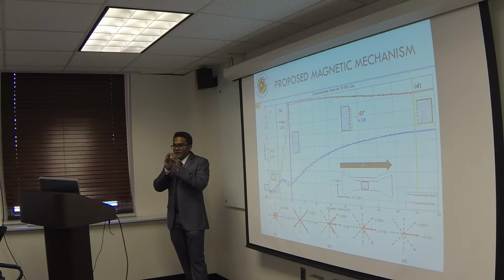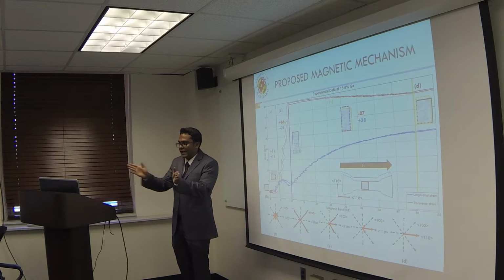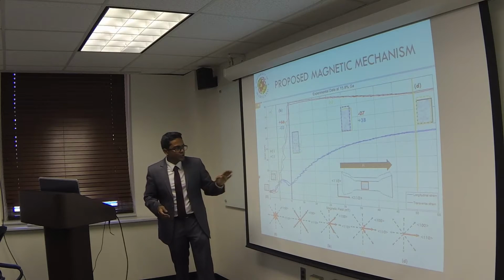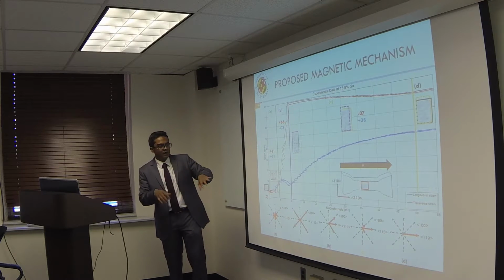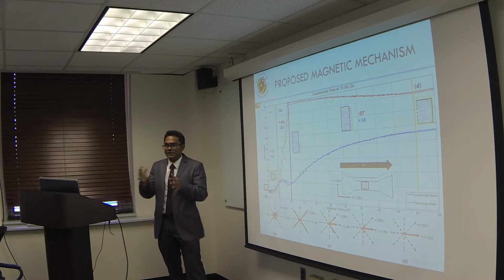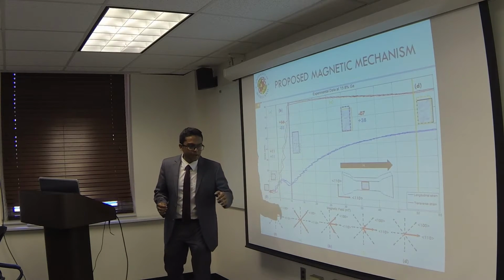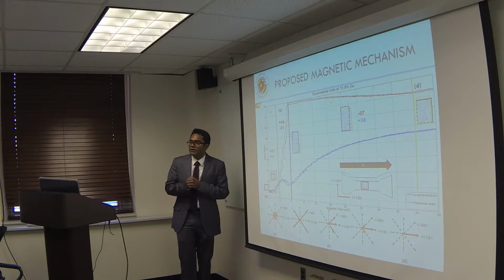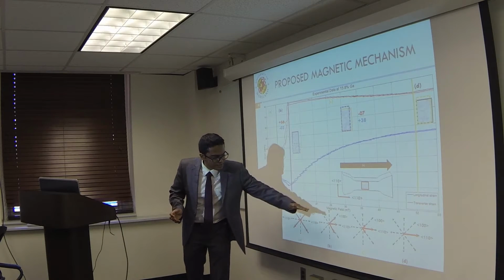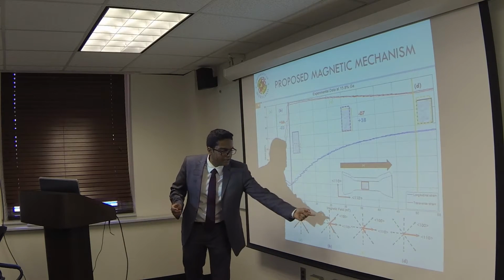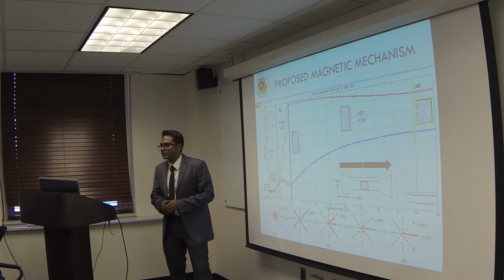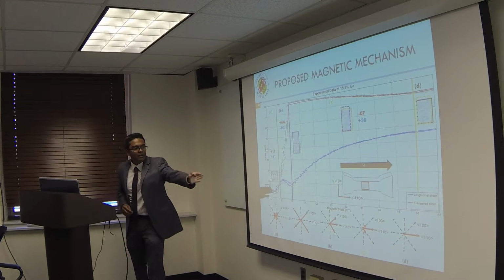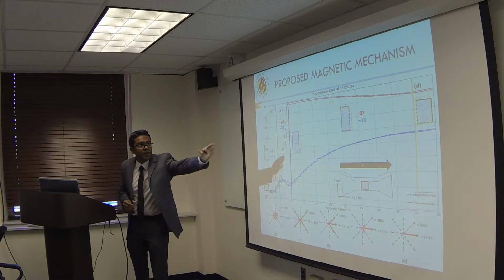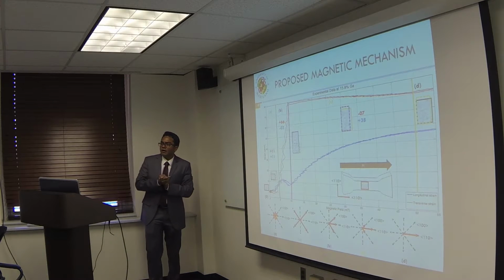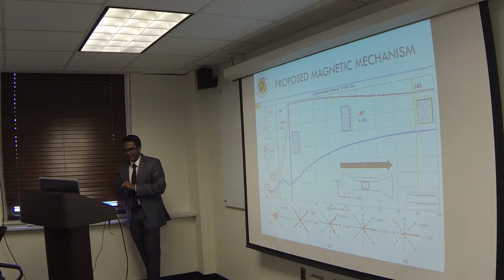So even if I put in magnetic energy along the diagonal, the energy still wants to flow along the edges of the cube. So that orients the dipoles along the 100 directions, which are easier to achieve. And now as I keep adding more and more energy along the 110 direction, that's going to cause some of the dipoles to start flipping over along the direction of applied field, which is the longitudinal 110 direction. And then we achieve magnetic saturation past D, where we have all the dipoles oriented along the applied magnetic field.